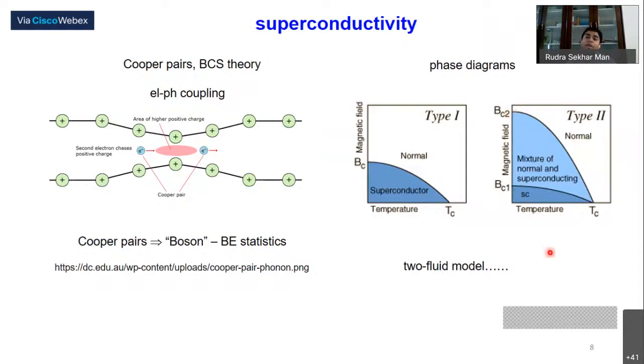That's why these type 2 superconductors are called, in the literature, high Tc superconductors. The name high Tc is a bit misleading. They call it high Tc because the Tc is above nitrogen temperature, and nitrogen is very much cheaper. So in that way, the temperature is somehow enhanced. If one goes to the history of superconductivity, a 100-year-old topic, initially the Tc was stuck around 30 Kelvin or so, but suddenly there was a jump from 30 to above nitrogen temperature. So that is really high with respect to the type 1.